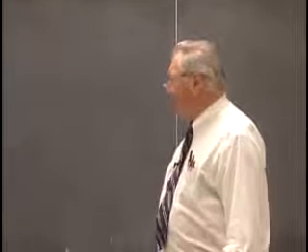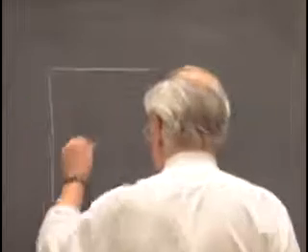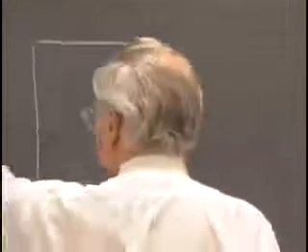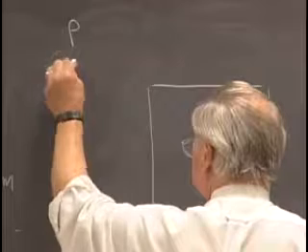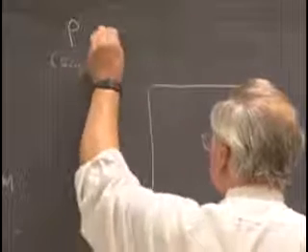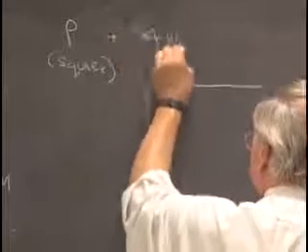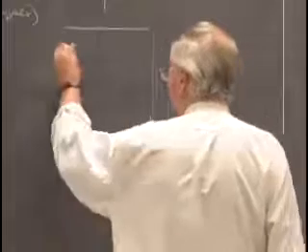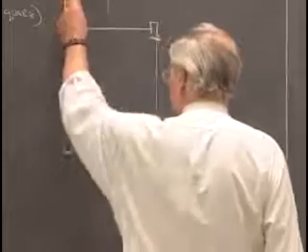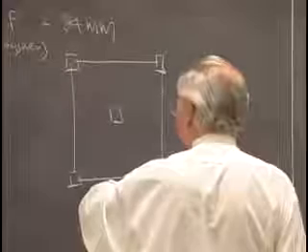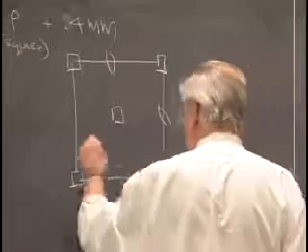Okay, let me move on then to the next step. And I'm going to skip over a threefold axis, and I'm going to look at the square net combined with the other symmetry that would require a net with this dimensionality, and this would be a primitive square lattice plus 4mm. We've already done almost all the work. So as we derive the symmetries that are subgroups of these higher symmetries, we've done P4, and that says that if we put a fourfold axis at the origin, we'll get another one in the center of the cell, and we'll get twofold axes in the midpoints of all the edges of the cell.